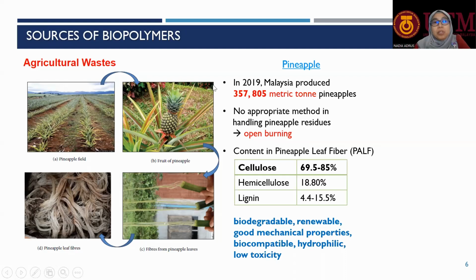And the most important thing is that the agricultural waste, especially from pineapple, is actually a source of biopolymers because it contains 69 to 85% of cellulose. Meanwhile, the rest of the components in the pineapple leaf fiber are hemicellulose and also lignin. So here we can see that the majority component of the pineapple leaf fiber is cellulose. And we know that cellulose is biodegradable and renewable, and this fiber from pineapple leaf has good mechanical properties, and studies have shown that it is also biocompatible, hydrophilic, and has low toxicity.